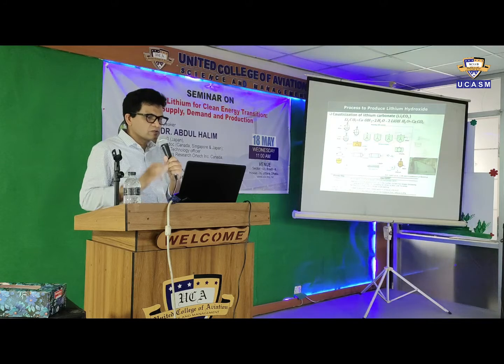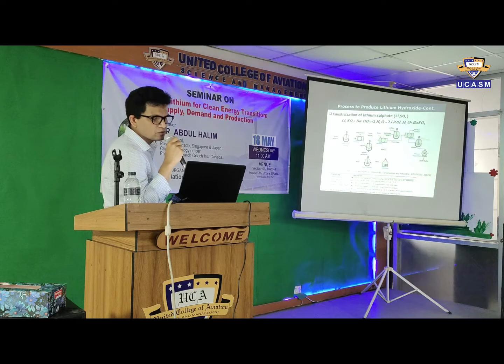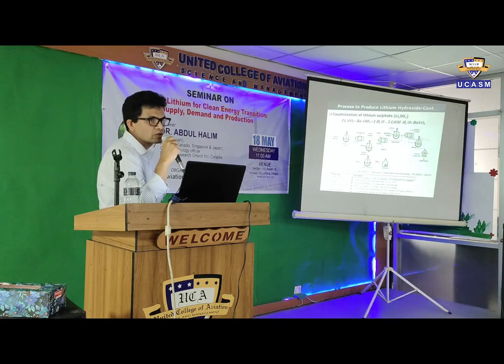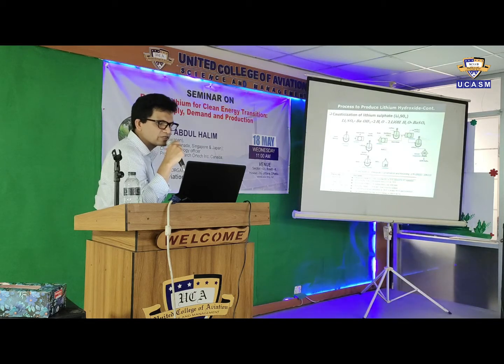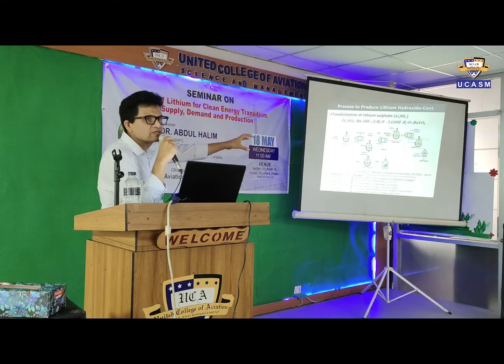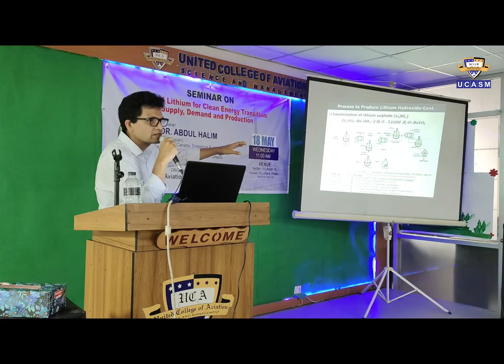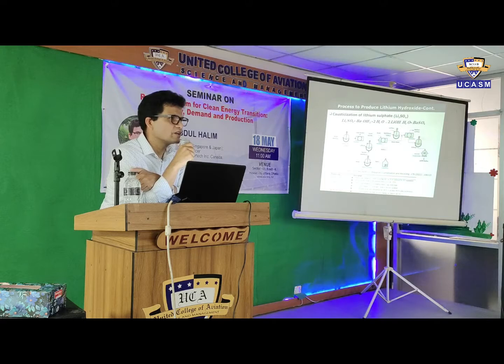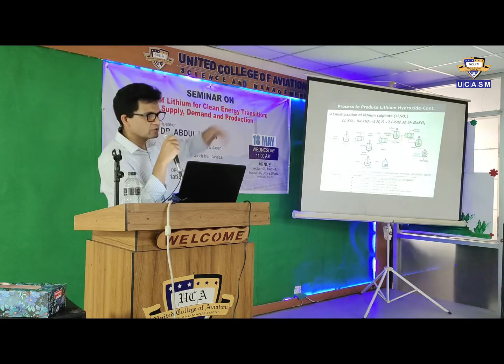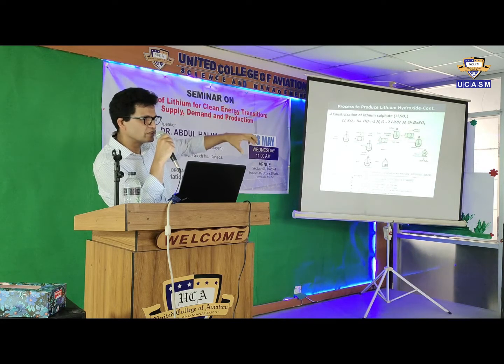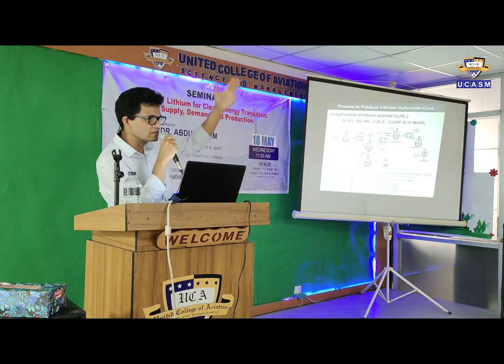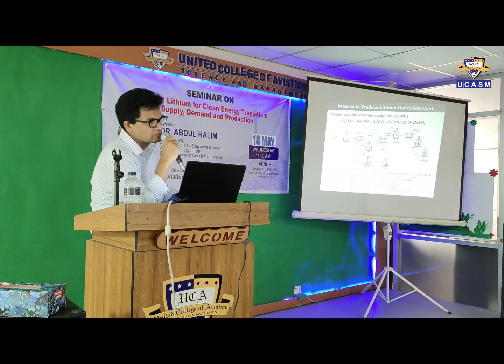So to overcome these issues, we are developing another process flowsheet. One of my colleagues, co-worker Dr. Azimi, is a professor at the University of Waterloo. She developed this process flowsheet and published it in 2022 in an Elsevier paper. What her group did: when these minerals dissolve in sulfuric acid, we get lithium sulfate. Instead of using calcium hydroxide, they use barium hydroxide. If you look at the periodic table, there is magnesium, calcium, barium, all in one group. Barium has special characteristics compared to calcium. Barium is more reactive toward sulfate compared to calcium.